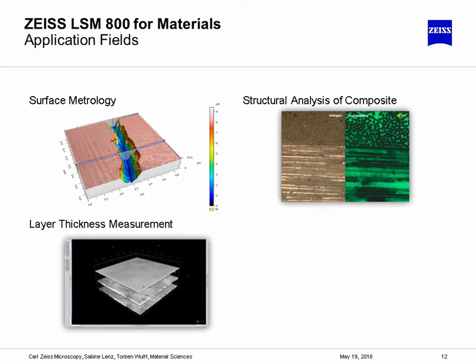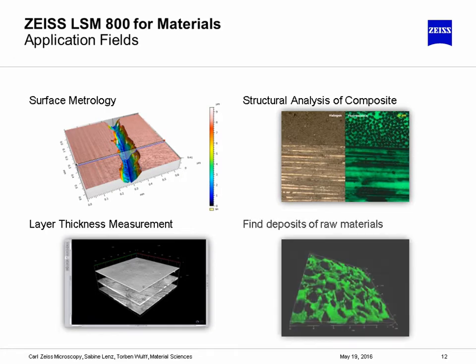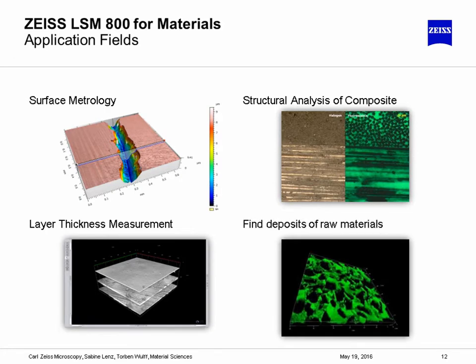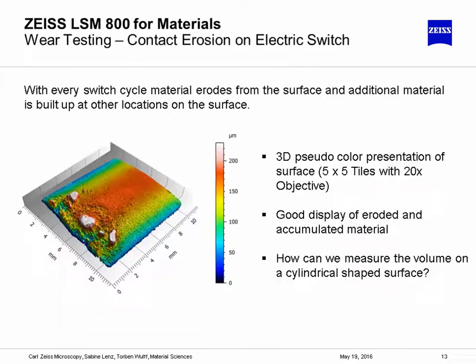Obviously, some structural analysis of a composite using different fluorescent modes can be performed, as well as layer thickness measurements. So in 3 dimensions here, the layer thickness can be measured using that same confocal technique. Also, for some porous materials, you're able to measure into pores and measure some of the porosity of these specimens.